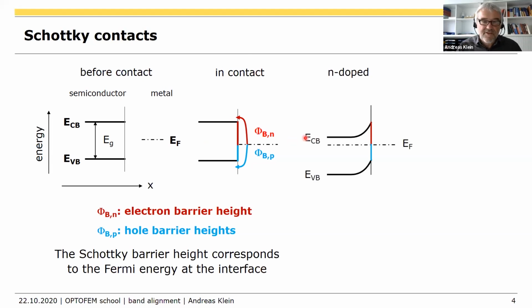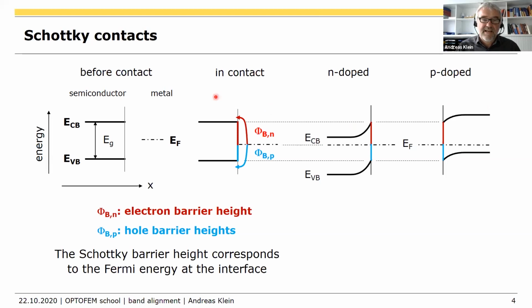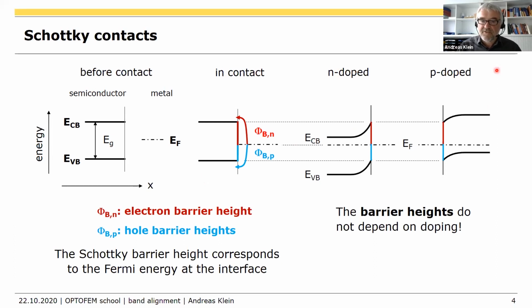Well, now there was no doping of the semiconductor, but you can easily add that. Take this interface, this semiconductor and this metal, and you make the semiconductor n-doped, you get a band bending in the semiconductor. If you make it p-doped, you get an opposite band bending. But you see that the distance to the Fermi level at the interface is the same in both cases. And it's also the same as in the case where there is no band bending at all. And that's very important. You can dope your material however you want, and that means the barrier height does not depend on the doping.